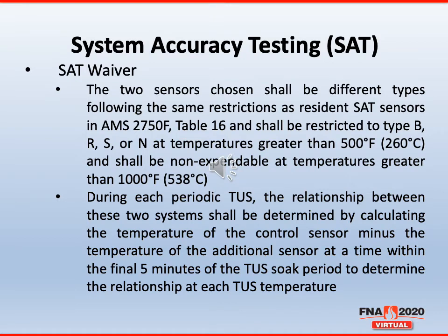During each periodic TUS, that relationship between these 2 systems shall be determined by calculating the temperature of the control sensor minus the temperature of an additional sensor at a time within the final minutes of the TUS soak period to determine the relationship at each TUS temperature. This is where you get your relationship that stays within the 2 degrees between the 2 existing sensors.